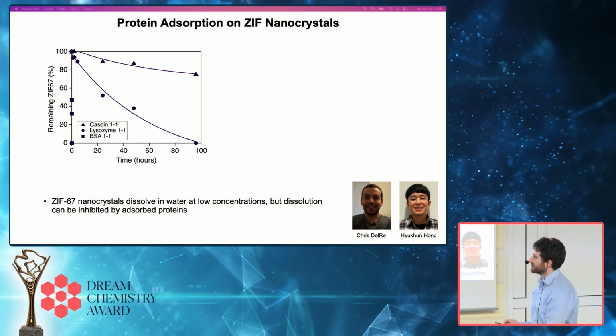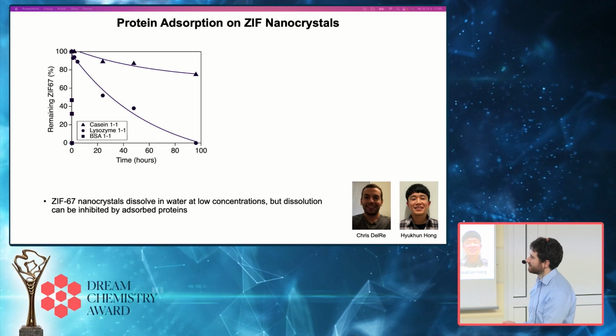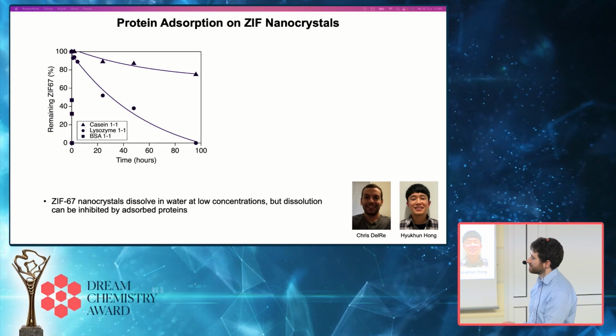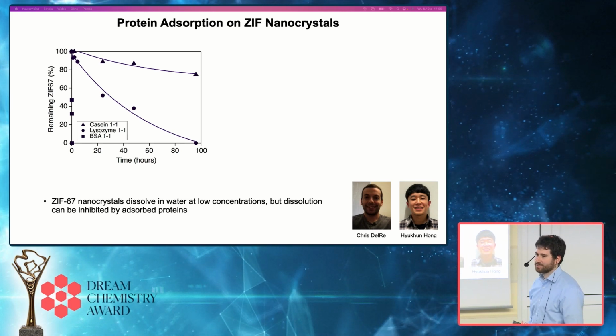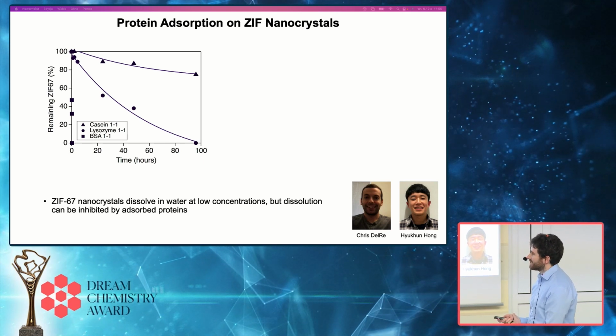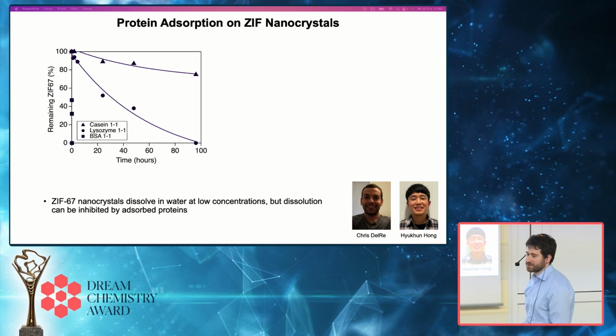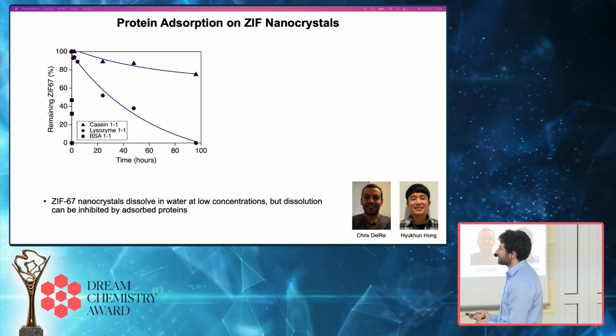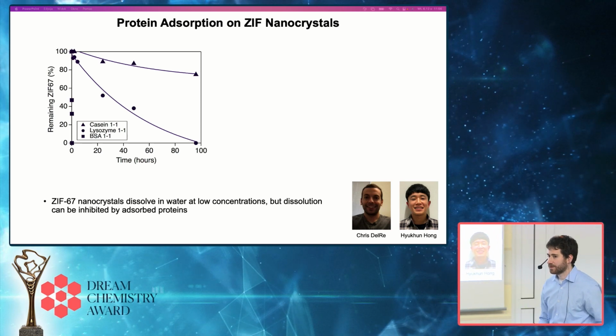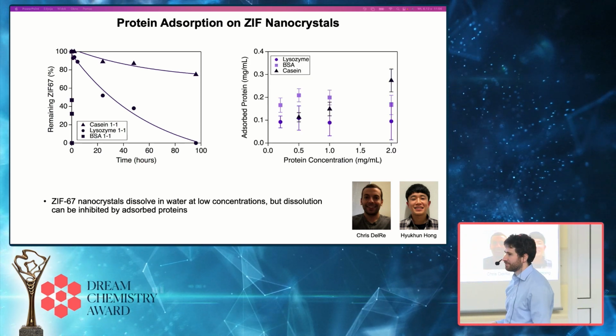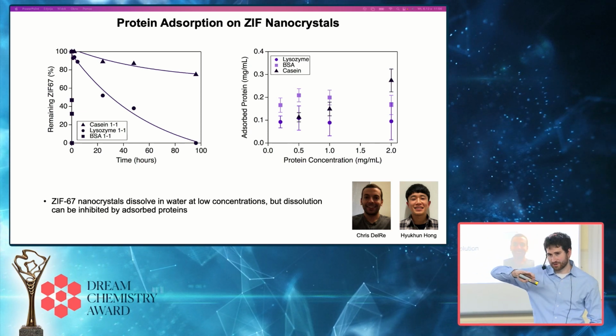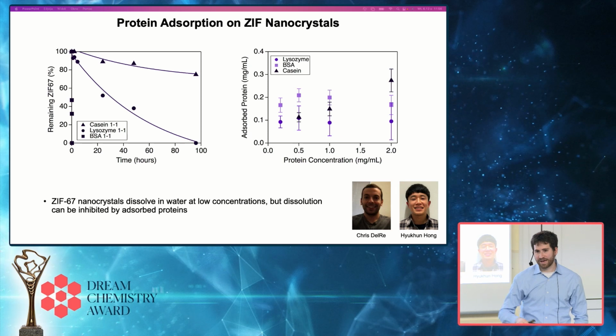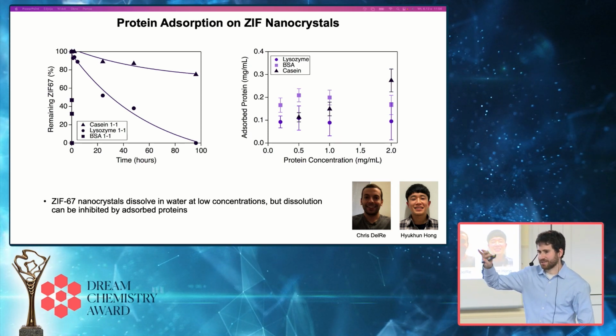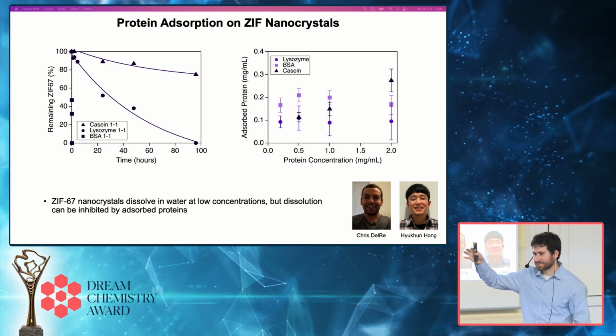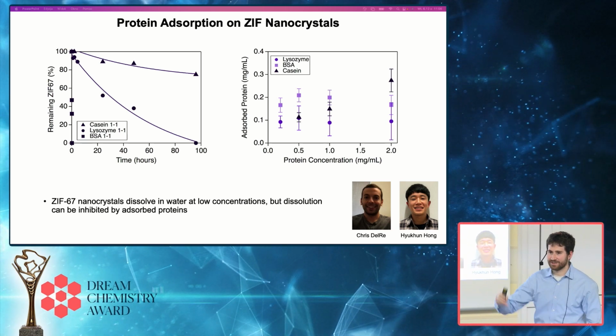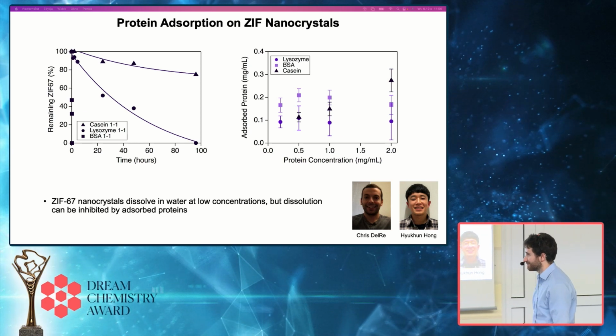And so what we find is that if you go from, say, casein to a positively charged protein like lysozyme to a negatively charged protein like bovine serum albumin, we see very different behavior in terms of the stability of the MOF particles. With BSA at low concentrations, these MOF particles dissolve within a matter of minutes. With casein, we see particles that are very stable for much longer periods of time. This is something we're still trying to understand. We don't think it's an effect of how much protein is adsorbed on the external surface of the particles, but more an effect of how the proteins are packing together and altering the solvation shell or hydration shell of the particles, and how they're controlling access of water to the pore surface. And this is something, again, we're still working to understand.